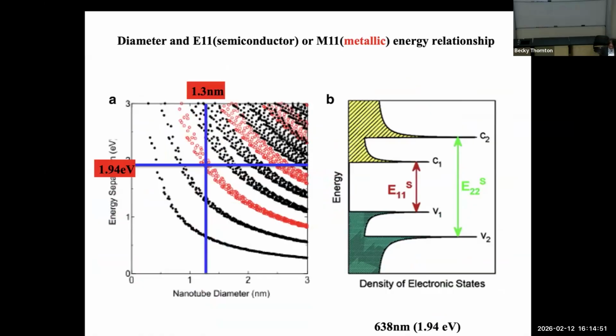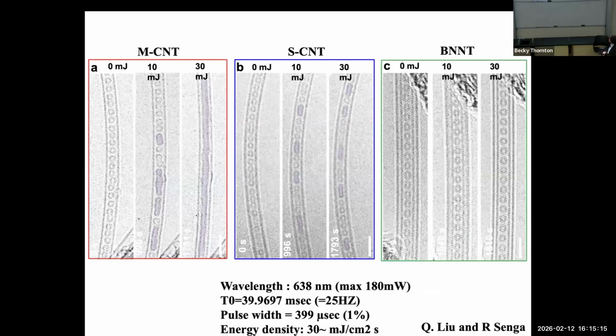It's a bit of a long story. We chose this 1.94 eV laser, and in this case only the metallic tubes can be excited. For the other tubes, it's transparent. Then this is very interesting result: if you are using metallic nanotubes, semiconducting nanotubes, or boron nitride tubes. Boron nitride has a 7 eV band gap, so all the laser light goes through, and there's no interaction. It's completely transparent, so no chemical reaction happens inside. This is very clear.